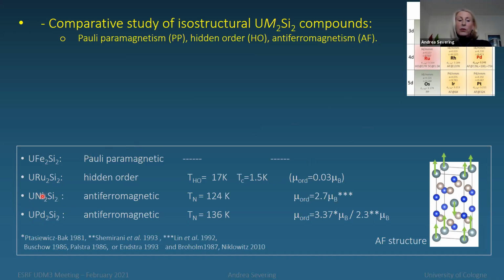And we have chosen the nickel and the palladium compound. The two of them are isoelectronic, and they have very high antiferromagnetic ordering temperatures and very large ordered magnetic moments. All four compounds have in common the same crystallographic structure, and if they order magnetically, they have the same ordered magnetic structure, that is ferromagnetic planes that couple antiferromagnetically along the c direction.